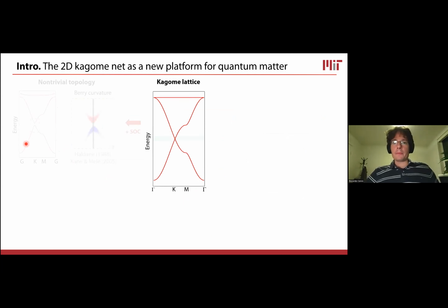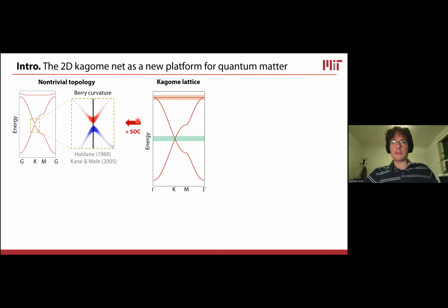So indeed, if we look at the different features of the Kagome lattice, as I was just saying, you can have localized sources of Berry curvature at all points where you have degeneracy. So that would be the K point and the degeneracy between the 2 Dirac bands, and the gamma point where you have a quadratic band touching point between the Dirac bands and the flat band.